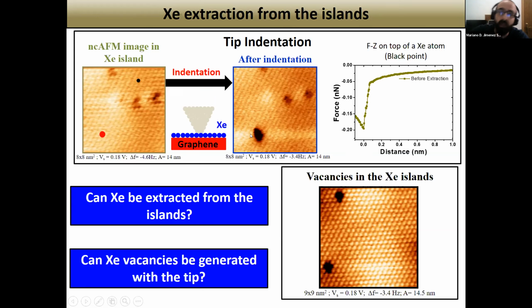And what has happened to the tip? Well, we again perform force spectroscopy, acquiring a force distance curve on the same point. And what we observe is that the maximum interaction has been reduced. And what does it mean? Well, it could mean that we have a less reactive species at the tip. So maybe we have a xenon atom. Nevertheless, this vacancy is big. I mean, it doesn't seem like a very controlled process.